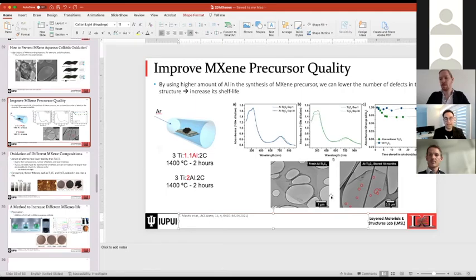is that when we have excess aluminum, although we form impurities such as intermetallics, the structure of the MAX phase, because we have more aluminum, we have more titanium, will have fewer defects, fewer vacancies of titanium and carbon in the structure, because we know all of the carbides, including MAX phases or the binary titanium carbides and others, are always non-stoichiometric. First of all, they have less carbon than we always write. For example, if you order TiC and buy it from any chemical company, it is never TiC. It is non-stoichiometric, and basically it's TiCx, where x is usually 0.9 or lower or higher, 0.95 or something like that. So if we can design a method to make a MAX phase that has fewer of these vacancy defects, then we'll have a higher stability.